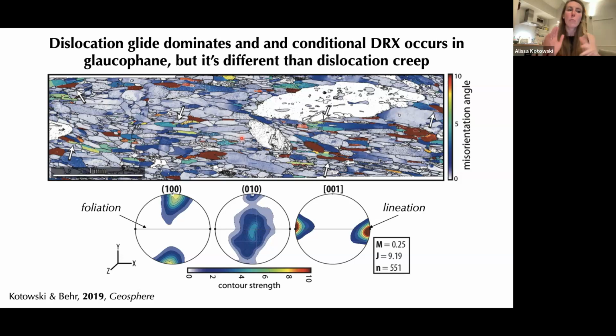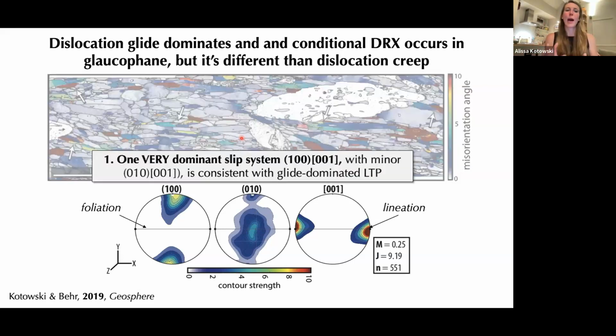dislocation creep. But I propose that this may be a mechanism that is quite distinct from dislocation creep in grain scale processes and actually in the recrystallization mechanism itself. So it is dynamic recrystallization, but potentially by a slightly different mechanism. And the reason for that is twofold. The first reason is that we have one extremely dominant slip system, slip on the A plane in the C direction, and almost no contribution from anything else.